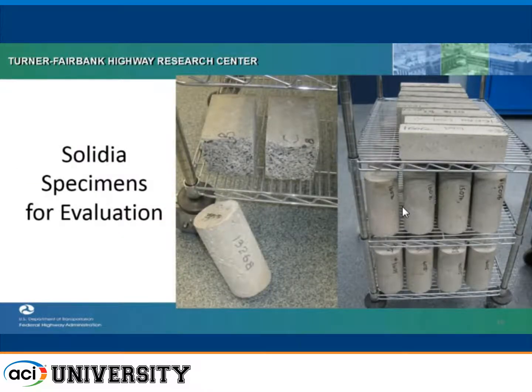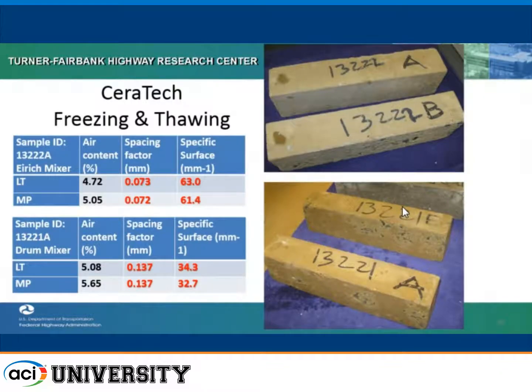Here are some of the specimens that we have on hand for future testing, and an example of a flexural specimen that was already broken. With CeraTech, we've done freezing and thawing work with it. We actually mixed two batches in two different mixers, basically the same material. One was in a high-energy vertical shaft mixer, and the other was in an ordinary drum mixer. The freezing and thawing durability results are pretty good on both, and again, a little bit of scaling. But it's interesting to note that the spacing factor with the high-energy mixer is about half of that of the drum mixer. So we were making smaller air bubbles with that high-energy mixer.